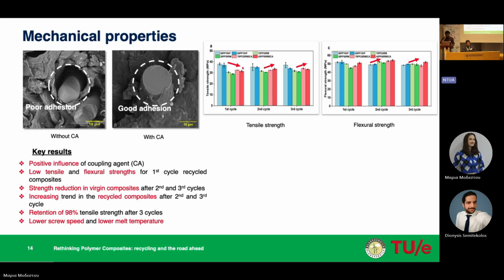Later on we also did some tensile testing and flexural testing. As expected, in the first cycle, we got lower tensile properties and flexural properties for recycled composites compared to virgin composites. And the recycled composites with coupling agent were able to achieve somewhere around 86% of the tensile strength of virgin composites.